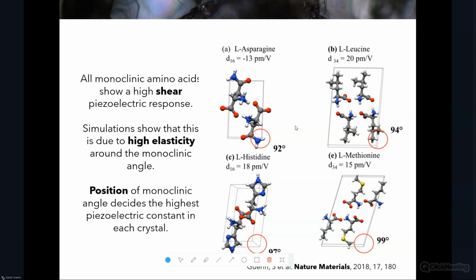So we expanded out our models to look at all of the proteinogenic amino acids. We saw that a lot of them had very significant shear piezoelectricity. That means when you apply a shearing force along a particular axis, you'll get charge out, again, along one of your perpendicular axes. And we saw that this was directly related to the fact that they all crystallized in a monoclinic space group. And the monoclinic angle allowed for that really high hinge flexibility that would generate a lot of ionic displacement and a lot of voltage out of these materials.